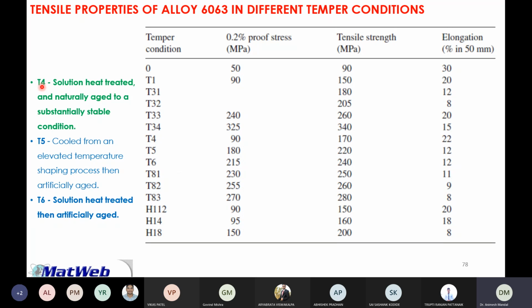For example, just to show you one example, T4. T4 is a naturally aged condition, where the alloy is naturally aged. You can see these properties: around 90 megapascal yield strength, 170 tensile strength, and 22% elongation. With the same alloy, now if you go for artificial aging, which is the T6, you can see the strength increases to around 215. That means in T4 it is 90, in T6 it is 215. Similarly, the ultimate tensile strength also increases from 170 to 240. But what you're compromising, or sacrificing, is the ductility.